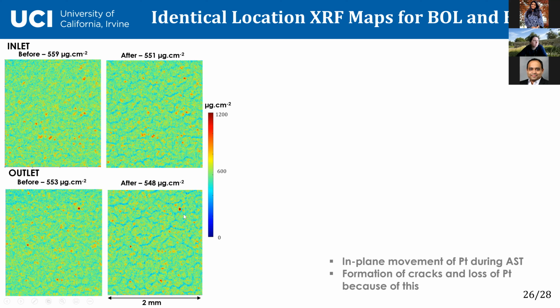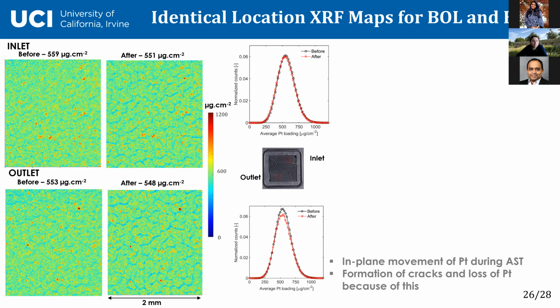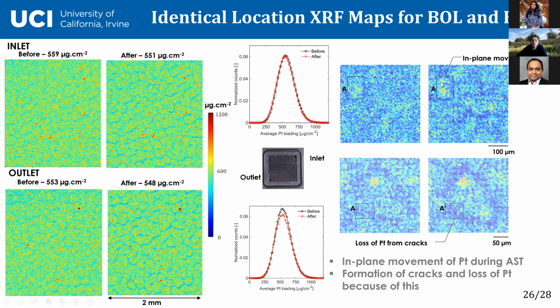And that's because, you know, cell undergoes dry out and dehydration, those dry wet cycles during operation, and those cause swelling of membrane and formation of mechanical stresses actually. Loading loss, we did not see any loading loss. So platinum particle size increased, but loading remained the same. But we did see some interesting in-plane movement of platinum, which we found quite interesting, specifically when we have formation of these cracks here, how will platinum redistribute? So that was some interesting finding.